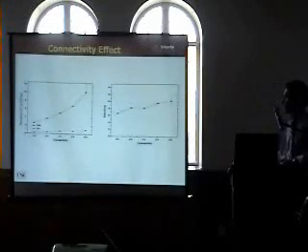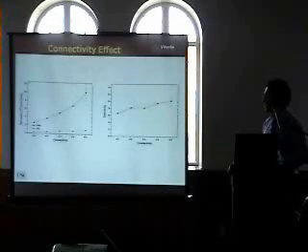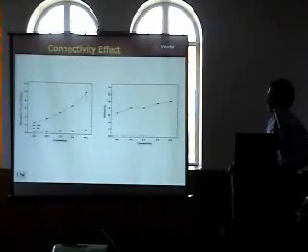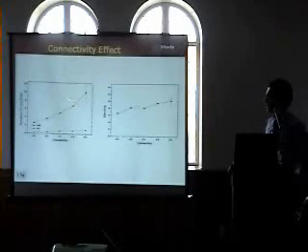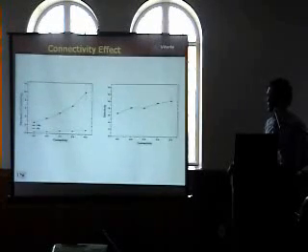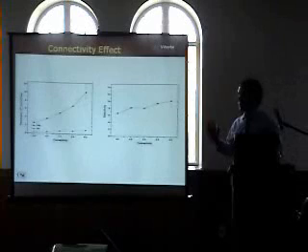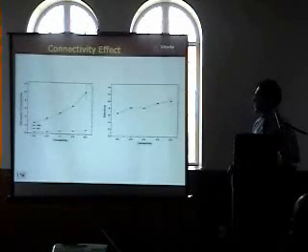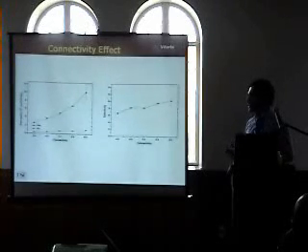And the last thing, but not least, we studied the connectivity effect. As you can see, as the connectivity decreases, the helium permeance decreases more significantly than argon. The reason for that is because we already considered the percolation effect for argon, but we didn't consider that for helium.